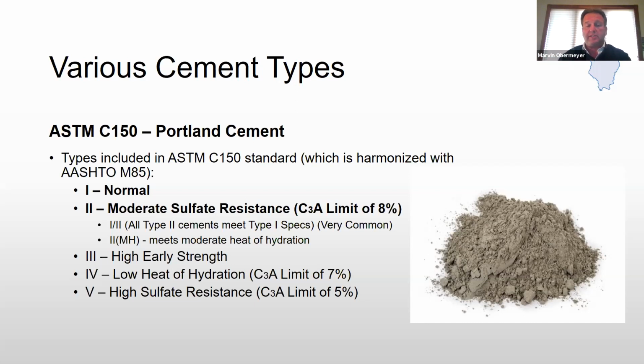Jumping around. Type 3 cement is a high early strength cement. The only difference between, in general, a type 1 and a type 3 is that the type 3 is ground finer, okay? And it will react. It actually has more surface area, okay? And the Blaine is higher. I'm going to explain that in a little bit.